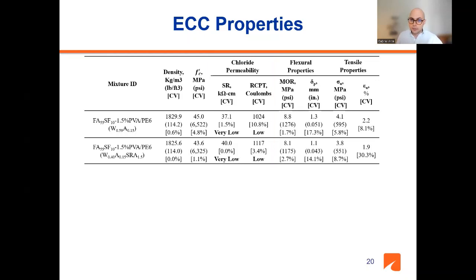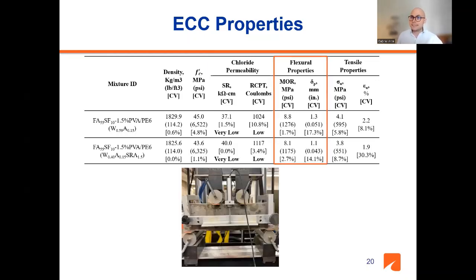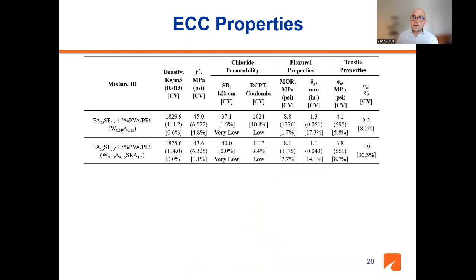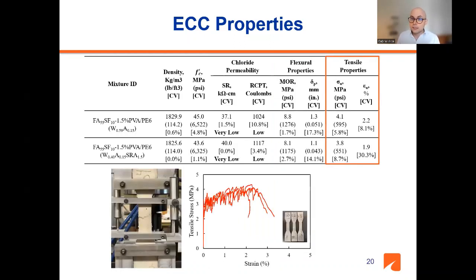Regarding the flexural properties, this is based on ASTM 1609, and I'm showing the picture below of the test. The flexural strength of these materials, about 8.8 megapascal for the one without the SRA. And this is roughly 2 times the flexural strength of conventional concrete. Also reported there is the deflection capacity of these materials. Finally, we have the tensile properties of these systems, around 4 megapascal, the strength in tension.